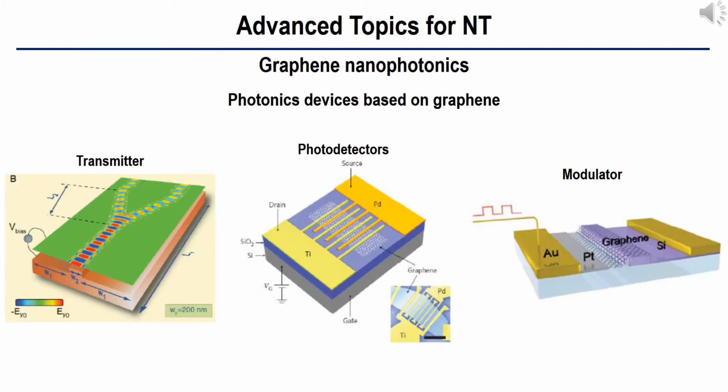Graphene's advanced photonic properties are advantageous in constructing waveguides for surface plasmon polaritons with long lifetime. By spatially varying the Fermi energy, we can fabricate an artificial structure with periodically changing conductivity. Then, surface plasmon polaritons can be reflected in a Fresnel-like fashion from the boundaries between the different conductivity regions. In particular, graphene photonics is advantageous for a broadband spectrum ranging from visible to infrared, from 514 to 2400 nanometers.